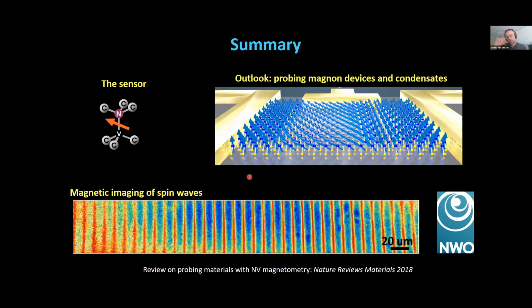There is time resolution, but you need to flip the NV spin. And that can happen only on the 10 nanosecond scale or so. So compared to pump probe optical experiments, this is very low. And I would say that it's very narrow band, although you are broad about 1 gigahertz, but if you compare it with Brillouin scattering, where you can go from half a gigahertz up to 300 gigahertz, it's of course very narrow band.